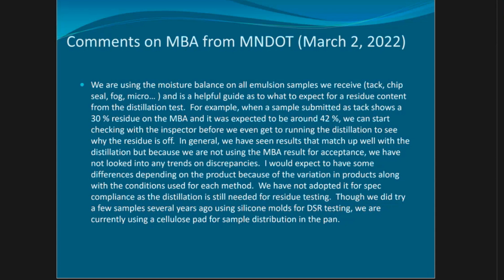Though we did try a few samples several years ago using a silicone mold for DSR testing. We are currently using a cellulose pad. That's what they're doing, a cellulose pad for sample distribution in the pan. So anyway, you see, you had several people independently look at this.